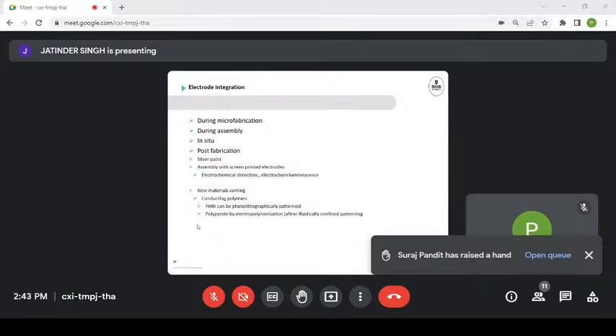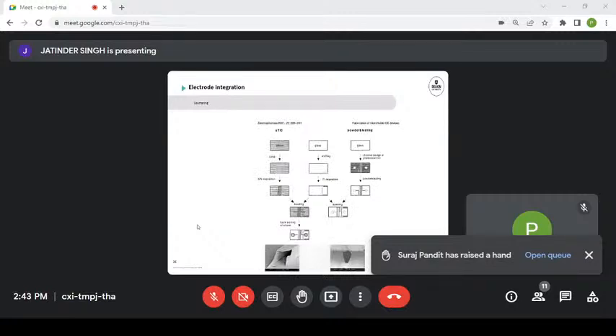And there's a growing collection of new materials, including conducting polymers, and that can also be all adapted for microfabrication. So sputtering is the very oldest way of putting electrodes in, where you get a mask to protect most of your substrate and you sputter an electrode on top. And the very early work I did on conductivity detection, these platinum electrodes, initially there were little trenches being etched for them, and then the electrodes were selectively deposited using a deposition mask into those trenches.